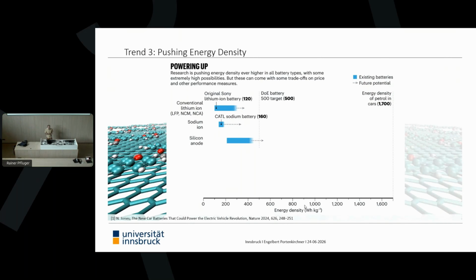You can see these blue bars. These are batteries that are confirmed, that are already existing, either on the market or working in laboratories. And then you can see arrows. And these arrows are what, to the best of our knowledge, we can estimate: with this kind of technology, how far can we push it in terms of energy density. And on top, you can see the common conventional lithium-ion batteries. The best in the laboratory have now already around 300 watt-hours per kilogram, but the material constraints, the science behind it, would still allow to increase it a little bit more to 400 watt-hours per kilogram.